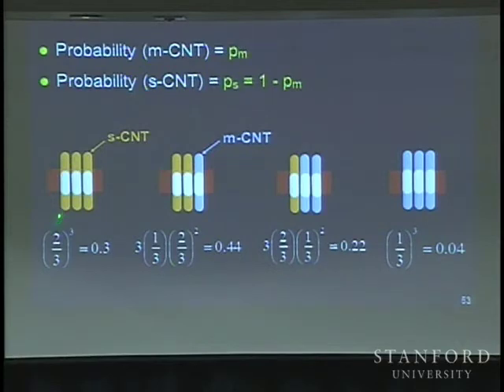Well, I could have a situation where all my carbon nanotubes are semiconducting, and that probability will be roughly around 30%, assuming that PM is 33%. I could have 1 or 2 of my carbon nanotubes to be semiconducting and the remaining are metallic. And I could have a situation where all my carbon nanotubes under the gate are metallic carbon nanotubes, right?